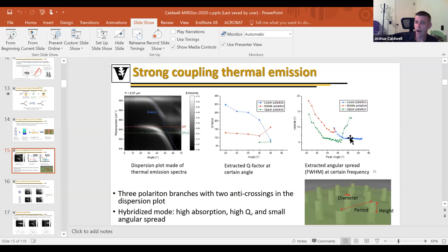So I'll put a caveat on this: the simple analytical expressions for, say, the Z extent of the evanescent field for a surface plasmon or a surface phonon polariton can give you a good estimation of this. The volume confinement does modify things. Off the top of my head, I don't remember exactly. But of course, the same general trends hold: at very, very low frequencies, the negative part of my permittivity is quite large, so I'm going to have a very weakly confined mode. As I go closer to the LO phonon, where the negative part of my permittivity becomes very small, I'm going to have a very highly confined mode.